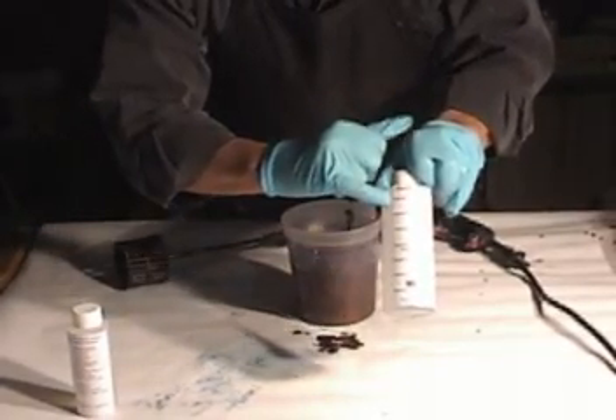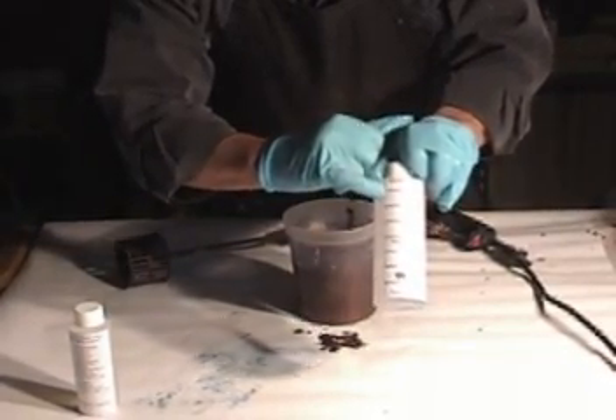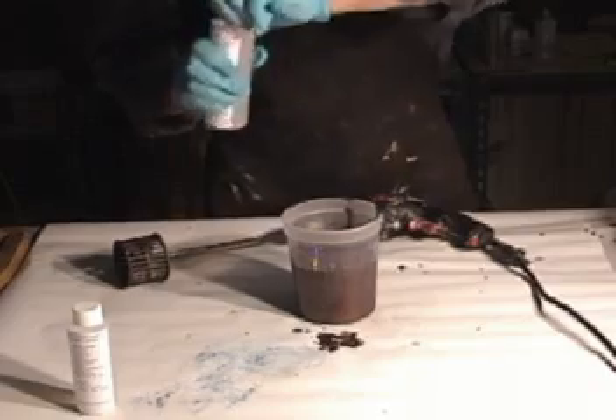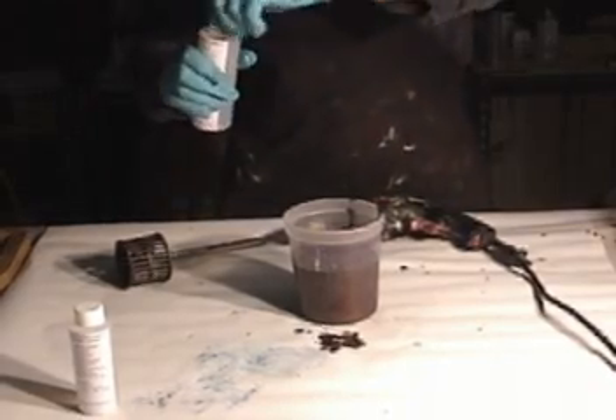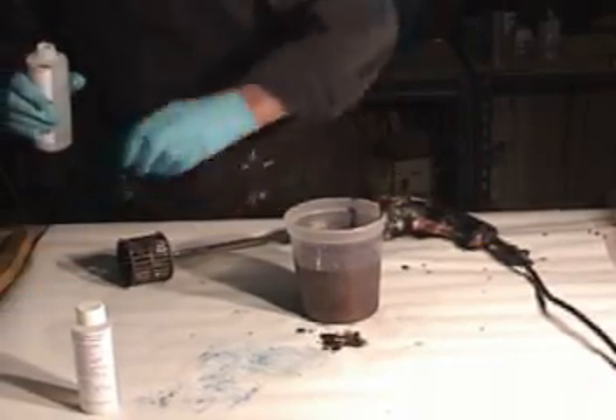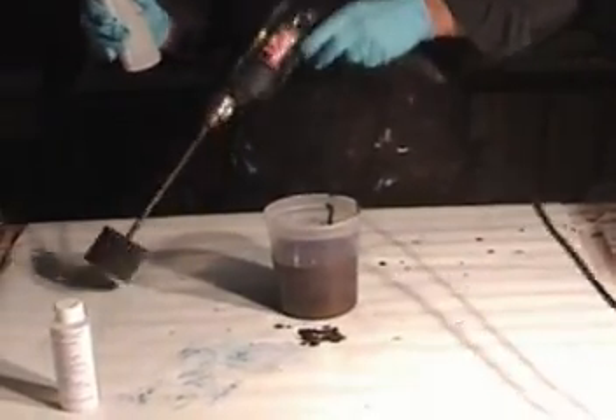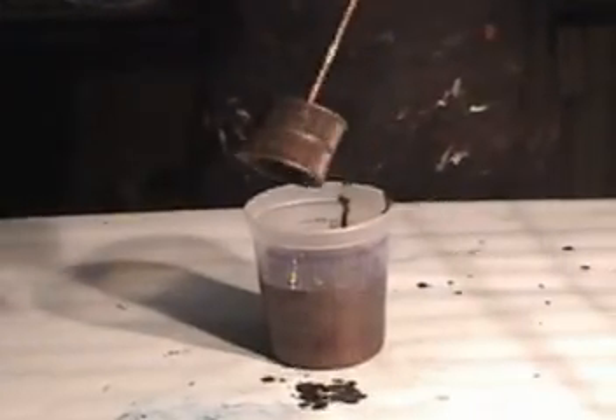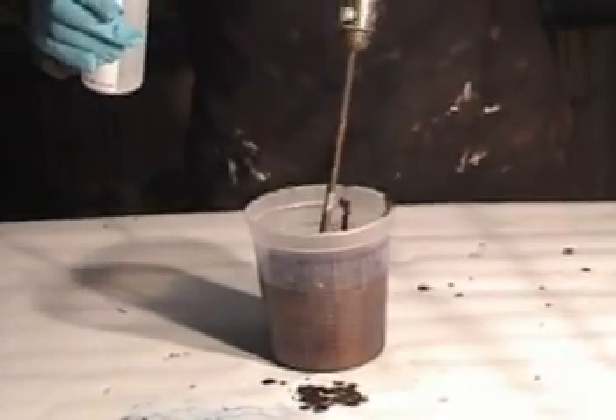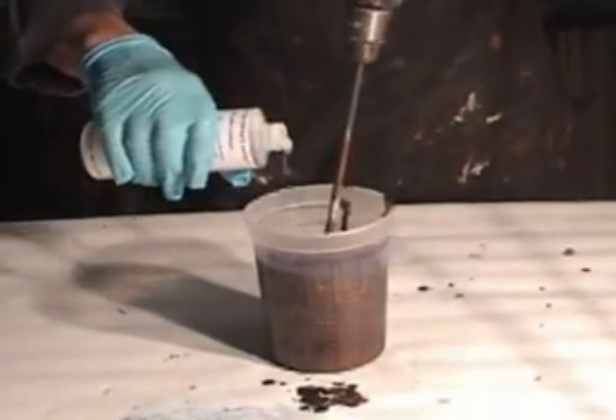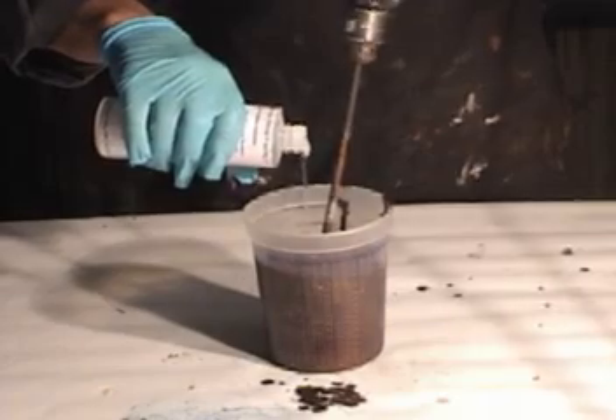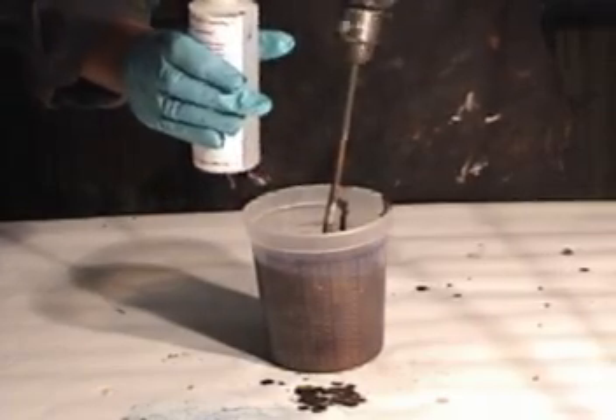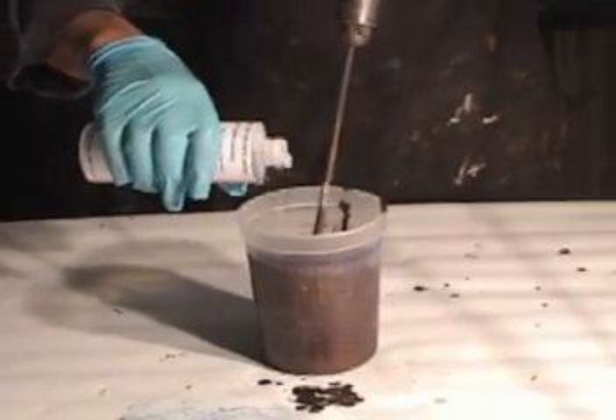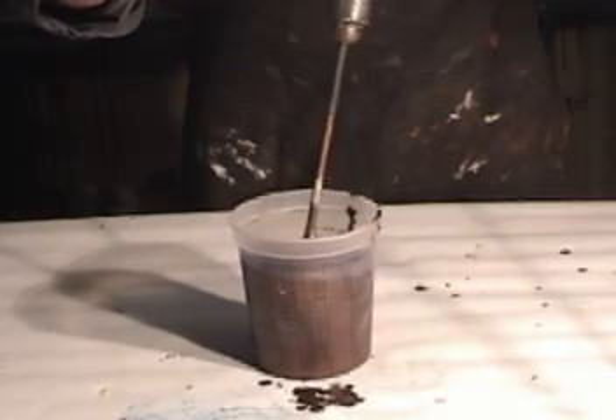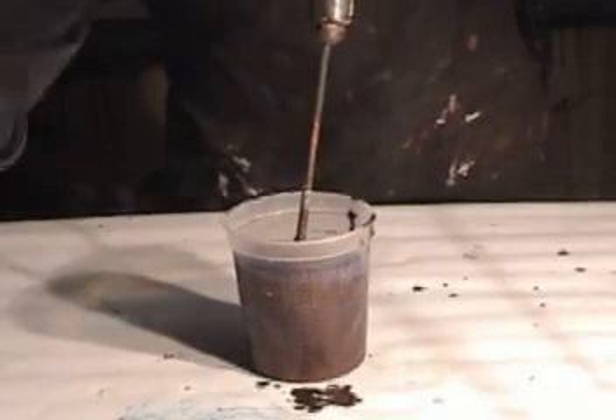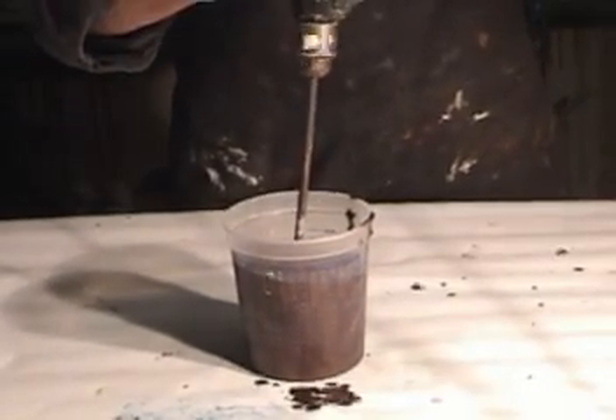Now we're ready to add the hardener. And you'll notice these little tick marks here are what we're going to go by. We want to pour out just to that first line, and that will give us the allotted amount of hardener for 16 ounces of paint base. Notice we're using a squirrel cage mixer to mix this in. And this way we don't have to worry about it activating too quickly by dispersing that throughout the mixture evenly. We don't have to worry about that kicking off too fast when we add the catalyst.